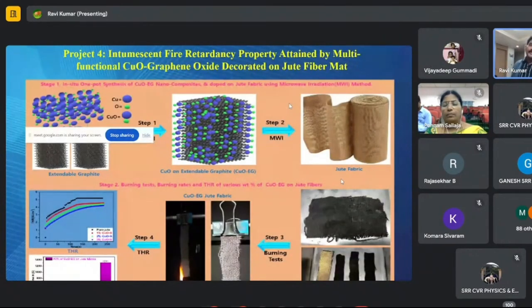Also, we studied the intumescent fire retardancy property attained by multifunctional copper oxide, graphene oxide decorated on jute fiber mat. Also, you can see this copper oxide and these expandable graphites. Those graphites we deposited on the surface of jute. This is the combination we developed, and later we deposited and checked the flame retardant test after deposition of this copper oxide, graphene oxide on the surface of jute.